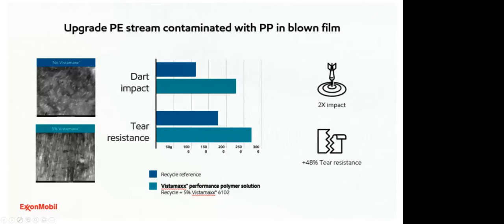This is shown on the morphology pictures on my left-hand side, where interfacial incompatibility is characterized by the spherical shape of the PP phase in the PE matrix in the top picture, and the addition of Vistamaxx 6102 shows that the PP phase follows the MD orientation of the film, acting as a compatibilizer. This increases the mechanical performance of the mixed polyolefin when PP and PE are recycled together.